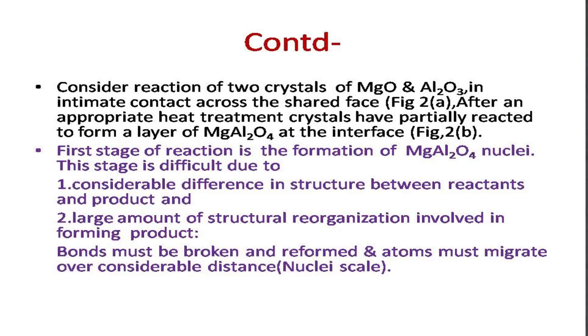Now, continuing with that, if you look at this slide, consider the reaction of the two crystals. You have placed MgO and Al2O3 face to face, and they are in contact across the shared face, which you have seen in part one of the diagram. After a certain number of hours, when they are heated under heat treatment, the crystals have partially reacted and a layer of MgAl2O4 is formed at the interface on both sides.